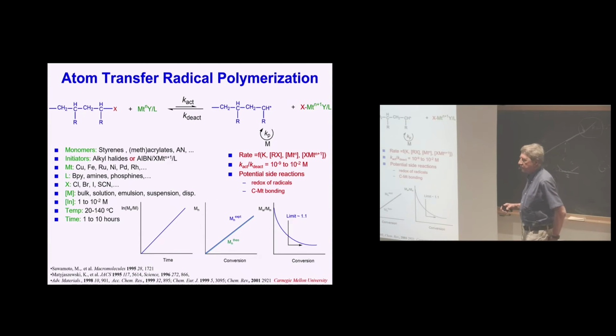Now, the third system, historically probably the second or first, is atom transfer radical polymerization. So you start with this inexpensive alkyl halide. They usually mimic structure of a dormant species. And then you add transition metals, such as derivatives of copper, iron, ruthenium, nickel, palladium, rhodium, sometimes also iridium can be used. And you need some ligands which would stabilize these radicals. They would like to be sometimes electron donating, as you will see, which would really favor formation of the sufficient concentration of radicals.